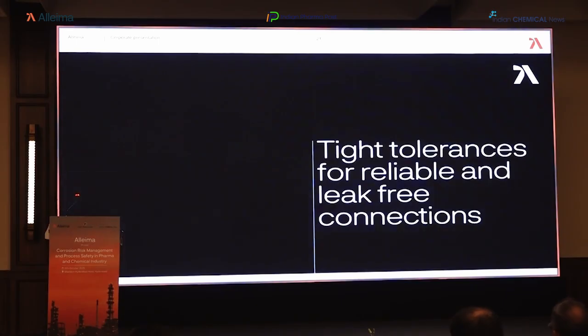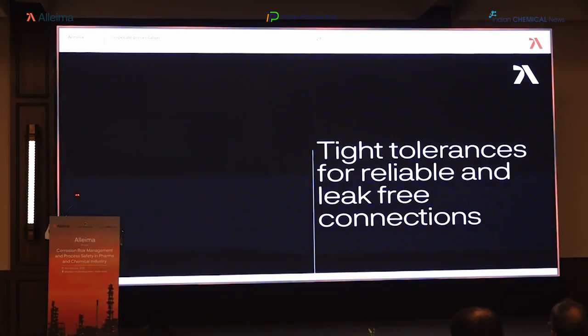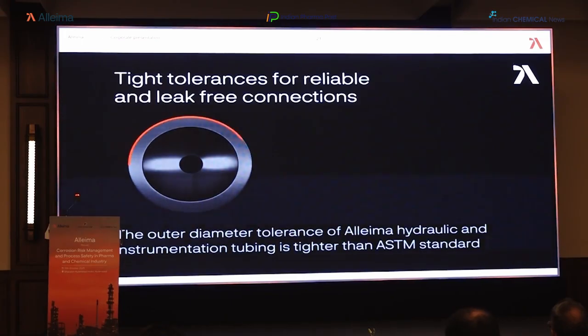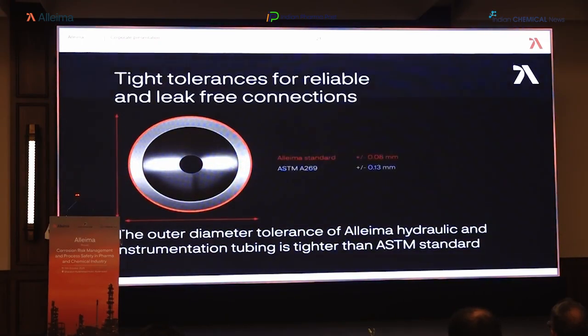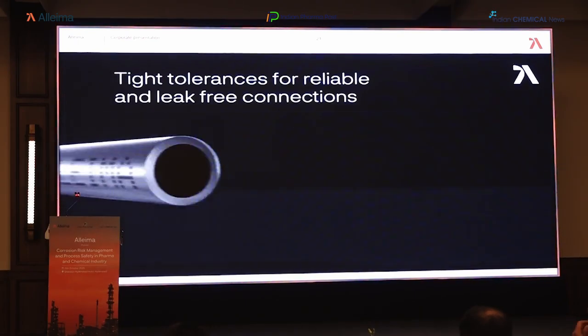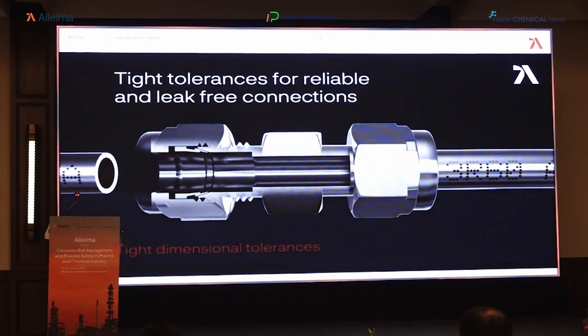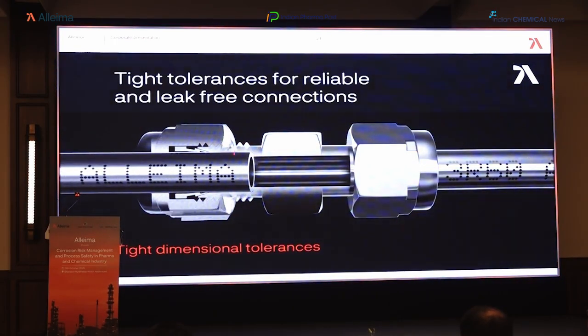Consistent ovality and tight tolerances set Alleima tubing apart and help prevent the risk of leaks. Our outer diameter tolerance often far exceeds the ASTM requirements. For example, for A269 category ASTM grades like 316 and 316L, the requirement is plus or minus 0.13 millimeters, whereas we consistently deliver plus or minus 0.08 millimeters with every batch. Naturally, a key benefit of our tight dimensional tolerance is a perfect leak-free connection.